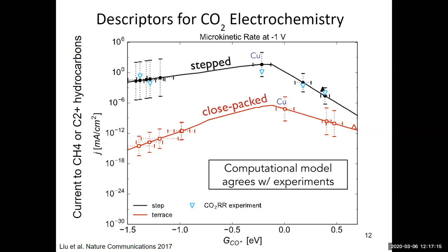So on the x-axis is the CO binding energy, the free energy. On the y-axis is either predicted microkinetic rates or experimental rates in those little blue triangles. And what we see is that there's a cluster of points over to the right-hand side. That's silver and gold with really weak CO binding. You make CO, CO doesn't want to stick around, it leaves. On the left-hand side, CO really wants to stick around to the point that you can't do anything interesting with it. And so you eventually poison your surface,